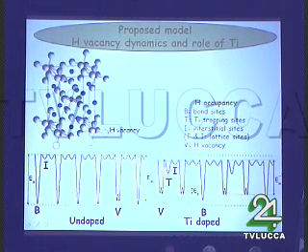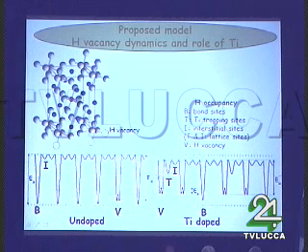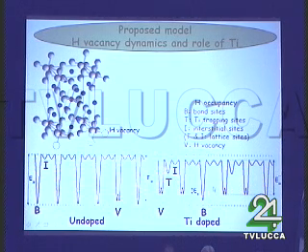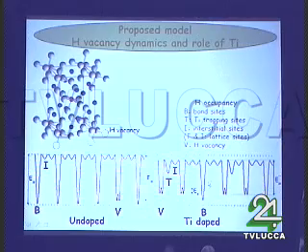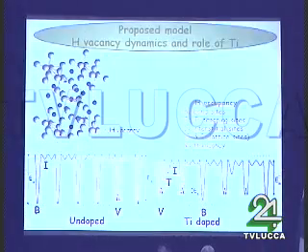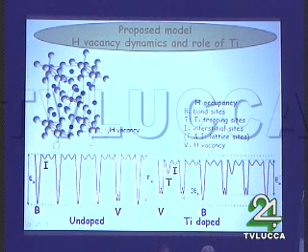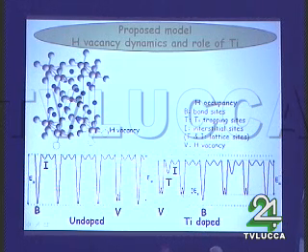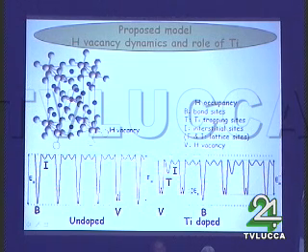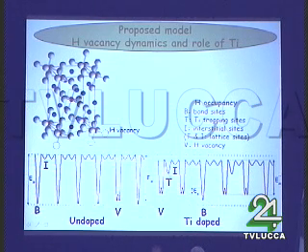So in this situation, we have a lowering of the decomposition temperatures, and in this picture we may have stoichiometric hexahydrides, or we can also have defective hexahydrides. When we have a hydrogen atom leaving the hydride, a multi-well potential is formed where the vacancy can relax with a lower creation energy, the one I showed you before, which is 0.12 electron volt. Titanium is a trapping site, and we also have this.